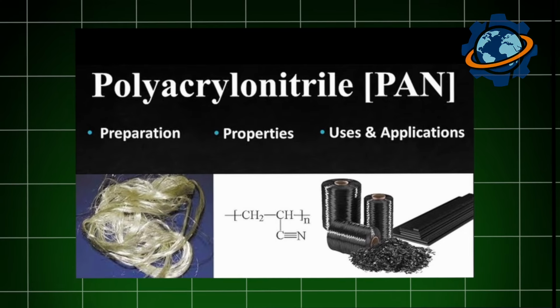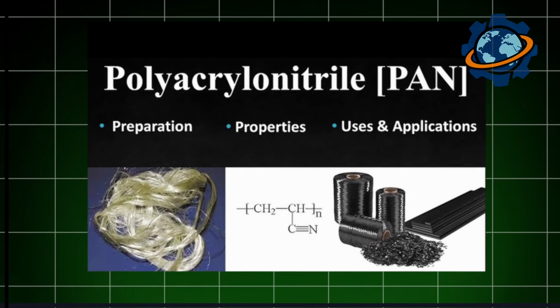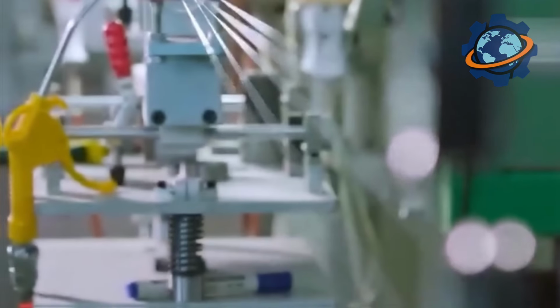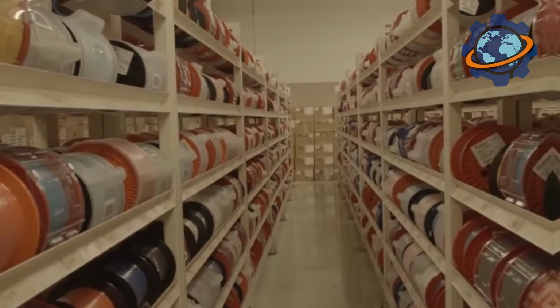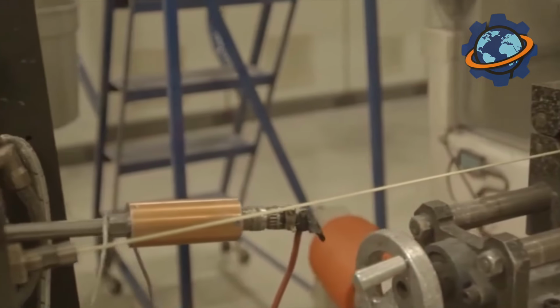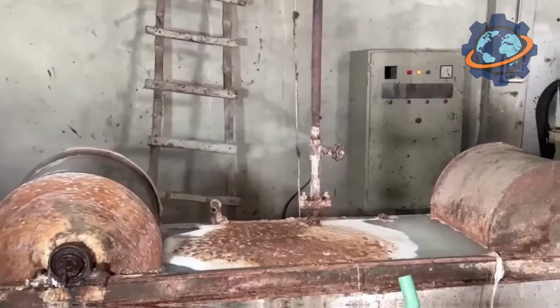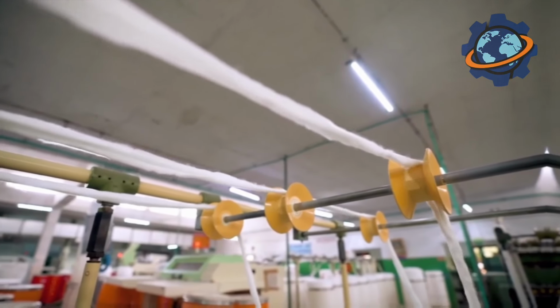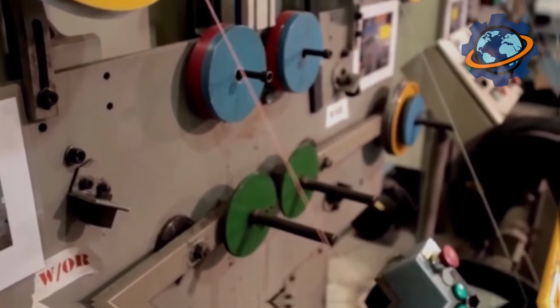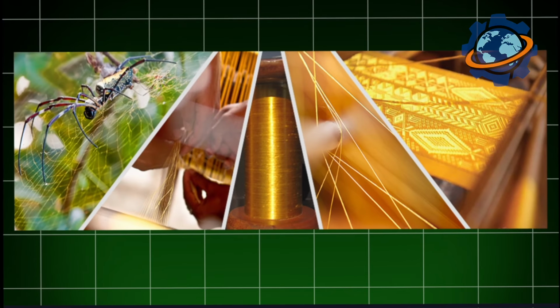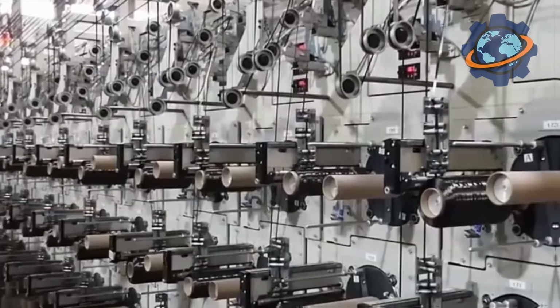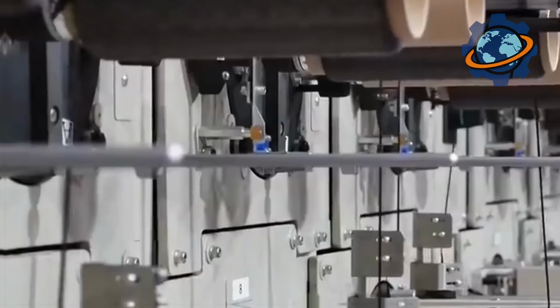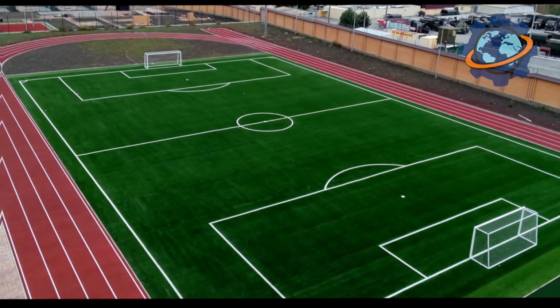The story begins with polyacrylonitrile, PAN fiber, the plastic precursor looking like white cotton thread. Massive spinning machines standing 3 stories tall in climate-controlled facilities extrude molten PAN through spinnerets containing 50,000 microscopic holes. Each hole, measuring 3/10,000ths of an inch across, thinner than blood cells, produces one continuous filament. Picture spider silk production scaled to industrial extremes. These filaments emerge at speeds reaching 3,000 feet per minute, fast enough to cross football fields in seconds.